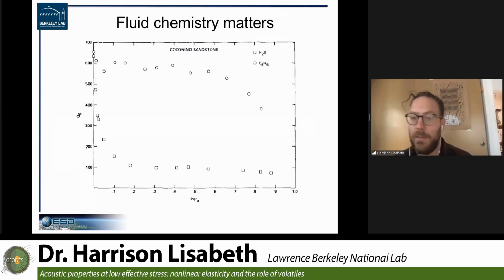But he went on to study the effects of other chemicals. So here we have Qs versus partial pressure, and this is water in the squares and benzene in the circles. And as you can see, water shows this dramatic drop off quickly, and then it flattens out. Whereas benzene, which is a non-polar molecule, doesn't have this same effect, and doesn't start to show a dramatic reduction in Q until much higher partial pressures. And that was interpreted to have to do with the adhesive behavior of the molecule on the surface, that being a polar molecule, water adsorbs strongly at first, and then there is at very high partial pressures another drop off of Q that indicates some sort of capillary condensation of the water. But for the benzene, you get very little adsorption effects, and you only get an effect once you start to have capillary condensation of the fluid.